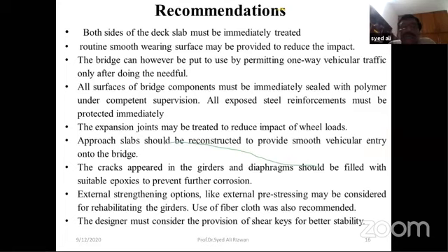The cracks appeared in the girder and the diaphragm should be filled with suitable epoxies to prevent further corrosion. External strengthening options like external pre-stressing may be considered for rehabilitating the girders. Use of fiber cloth was also recommended. The designer must consider the provision of shear keys for better stability. So this was our report. We remained there for about 7 days and then made calculations and material testing results. So the report was submitted after about 2 months.